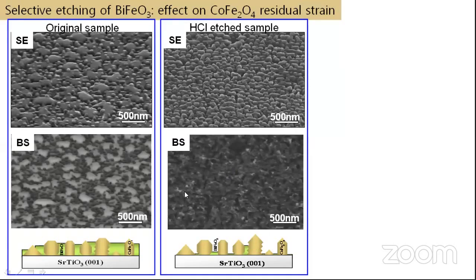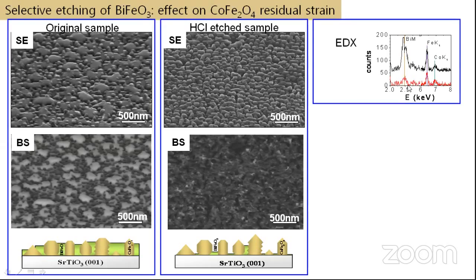This is the backscattered SEM image, which clearly shows that we have removed the bismuth ferrite, almost completely. And the EDAX pattern shows that the bismuth ferrite has been completely reduced after etching. This is the EDAX pattern before etching, and this is the EDAX pattern after etching. So this has completely removed the bismuth ferrite.